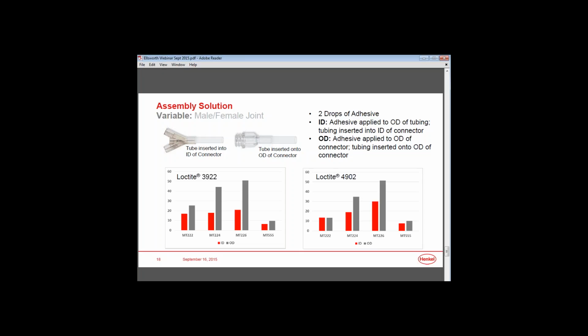So before we close, I just wanted to mention that Tom had talked about some of the applications in which he's seeing an increased request or desire for the TPEs, and one of those is in infusion. And typically for those applications, they're looking for around 5 pounds of bond strength, ideally 8 to be above that threshold. So for all the data that we presented here today, you'll note that the majority of the materials achieve at least that 5 to 8 pounds of strength, if not much greater. So for the most part, all the strength data is within the range of where these applications would need to be.